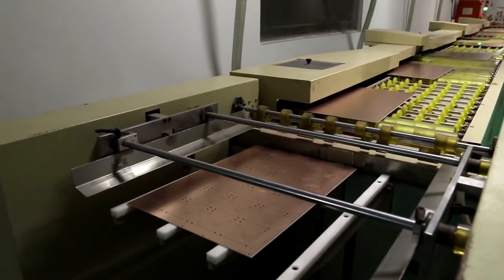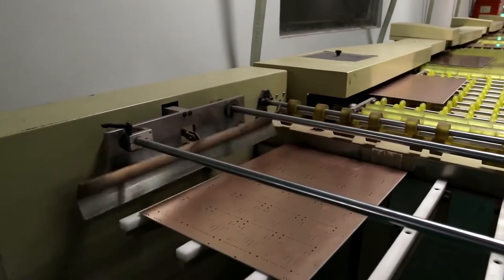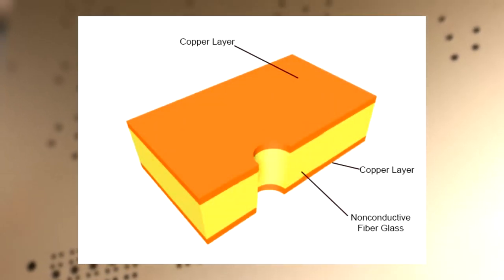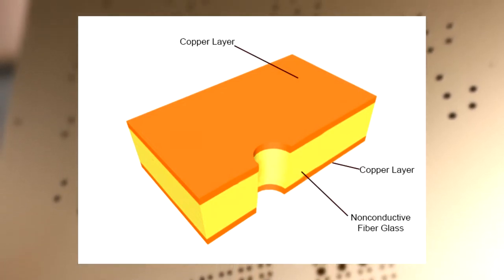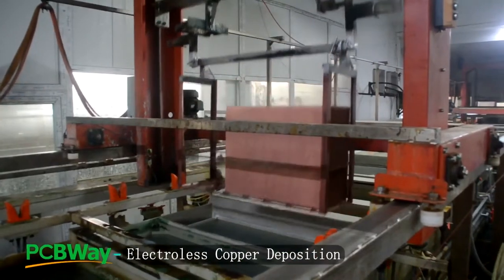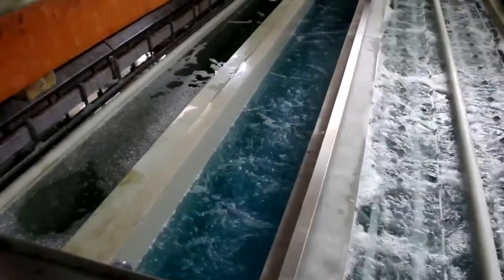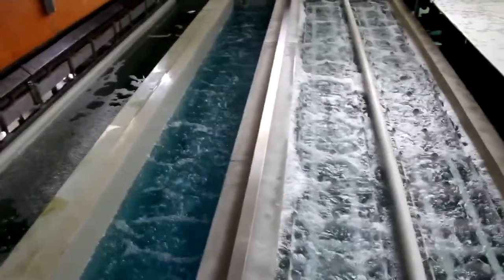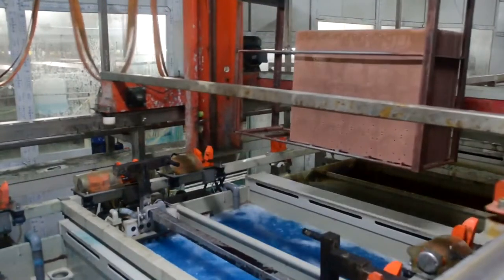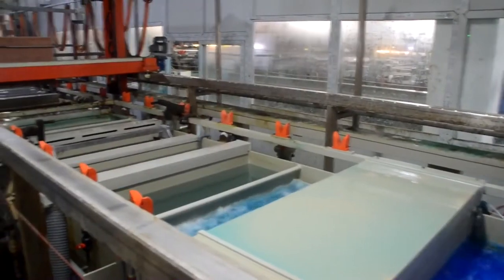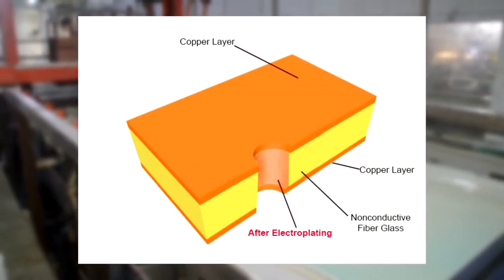As the board has been drilled for making connection between top and bottom layer, but the middle layer is non-conductive fiberglass, to make connection between top and bottom layer, the board comes for electroplating. The operator loads the panels onto the flight bars. The panels themselves act as cathodes for electroplating. The panels are carried through a series of chemical and rinse baths by the overhead crane. This is a multi-stage process, and everything is controlled by computer to ensure about 1 micron thick copper has deposited over the walls of the hole.